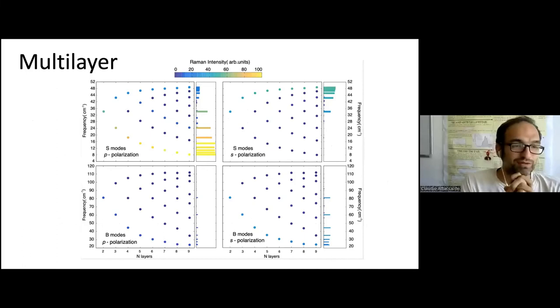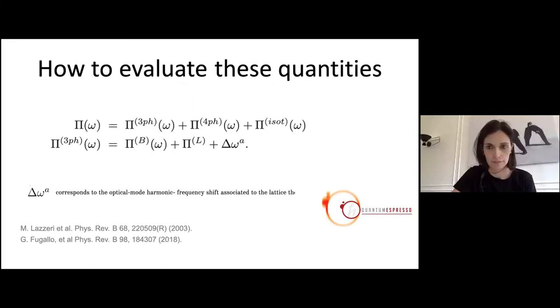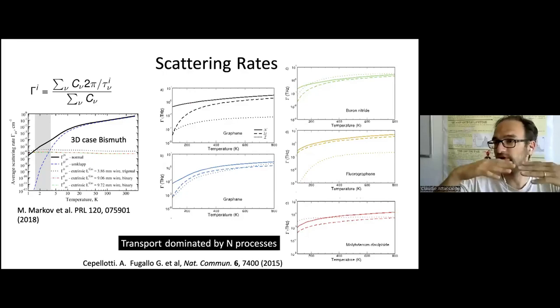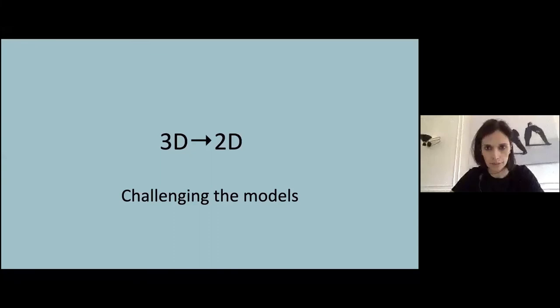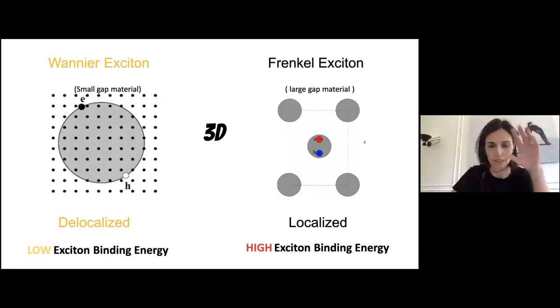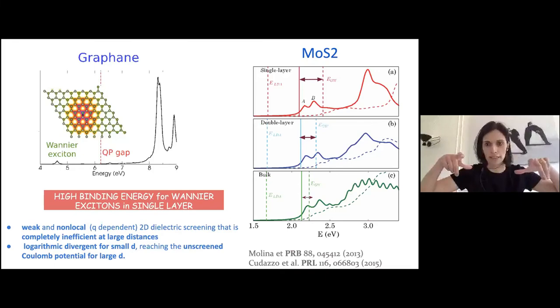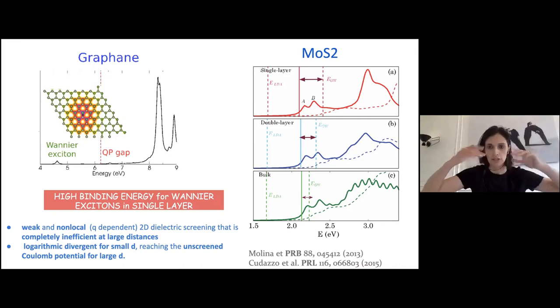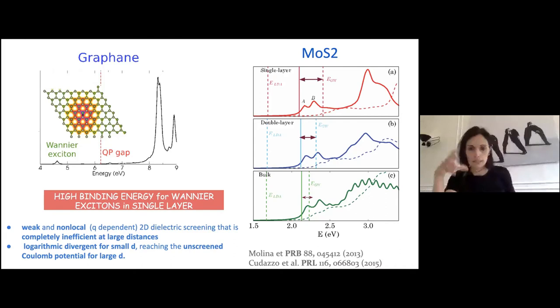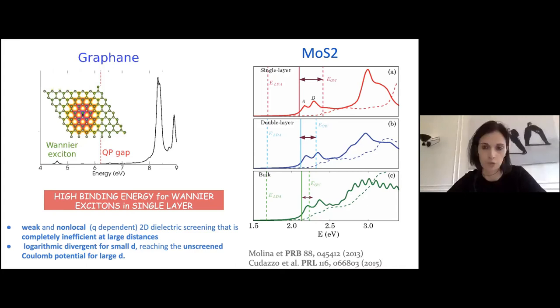Question: Thank you for the talk. I have a question on the first part — when you speak about transport in the system, the graphene is deposited on a substrate. Are the flexural phonons not suppressed by the substrate? Answer: The experiments presented were made on suspended graphene — there is a substrate with a hole, and the graphene is suspended over the hole, not sitting on the substrate. The dimension I was reporting was the dimension of the hole. Of course it changes a lot whether the system is on a substrate or suspended.